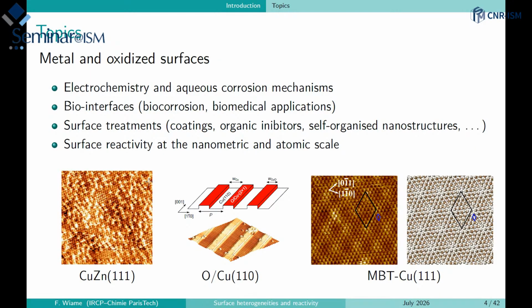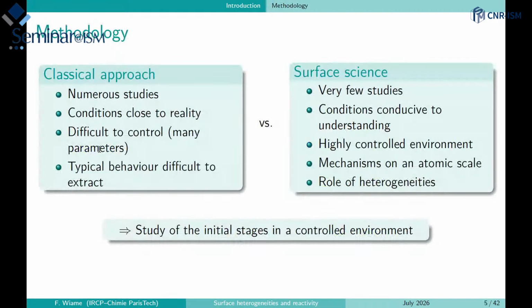And so I'm involved in the two last topics, and I lead the surface reactivity at the nanometric and atomic scale. So our approach to study the reactivity is quite different from the classical approach, which is generally based on a large number of measurements in conditions close to real ones. The problem is essentially related to the difficulty to control all the parameters that you have in real conditions, and makes things more difficult to extract some fundamental behavior.